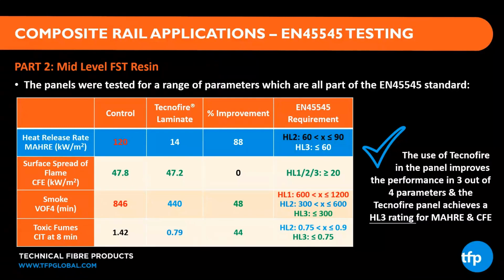But again, if we look at the improvement of incorporating the Tecnofire, we've improved that by 44% and dropped it down to 0.79. We look at the requirements, the HL3 requirement for toxic fumes is less than 0.75. So we're virtually on the limit of the highest level of performance to toxic fume standard with a halogenated system by incorporating the Tecnofire. And again, if you can loop back and think about the way the veil intumesces, expands, forms that stable carbonaceous char, it's preventing toxic fumes from getting out, fuel source from getting out, it's preventing heat and oxygen from getting into the laminate.